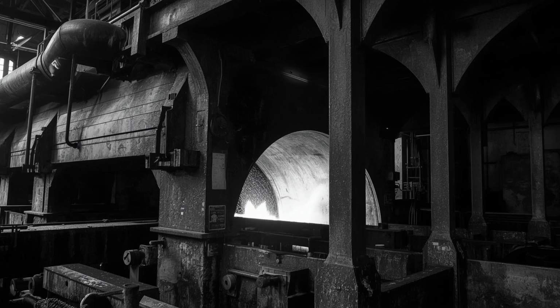The superintendent listened to all of them and made no immediate decision. He ordered the dampers closed further, then opened again, then returned to their original position. None of it made a difference. The temperature inside continued to rise. By this point, the refractory brick in the hottest sections of the furnace was glowing white. The outer shell had begun to radiate enough heat that men standing 15 feet away could feel it on their faces. The creaking of the metal framework became constant.